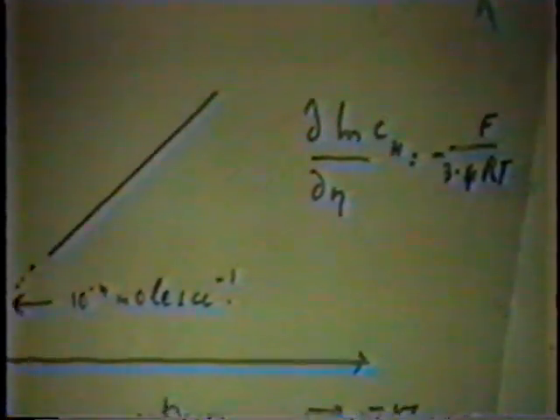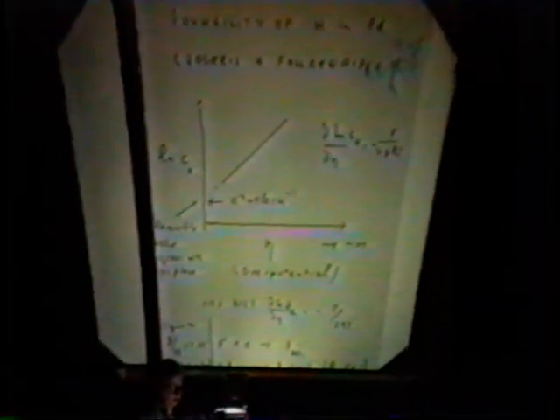d log C_H by d eta, how much increases the slope, came in this chap Fullenweider's work to minus F over 3.4 RT. Now that's a bit of a shivery value for electrochemists because they like nice integral values, and the integral value F over 4 RT makes a great deal of sense for us. And so I'm going to fudge a little bit and take this 4 RT in deciding what this implies for the mechanism. If I convert this C_H to fugacity, f_DH2, I get d log f_DH2 by d eta is minus F over 2 RT, and now I want to put back the thing where I have the fugacities and the open potentials. And you see there's only one which would correspond to that. It's this one, 2 RT over eta F.